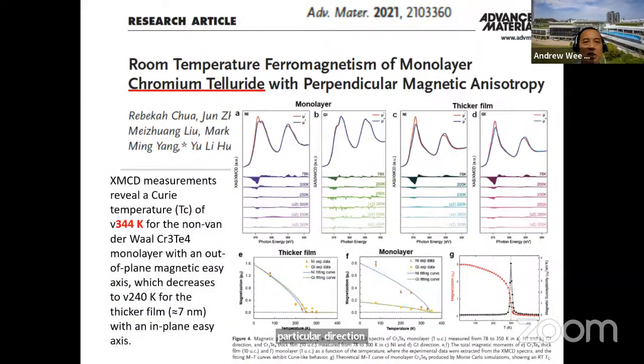So XMCD measurements reveal that it is possible to get a room temperature, above room temperature, Curie temperature for certain 2D magnetic materials. And in the paper, we suggest that interface effects may be one cause for this.